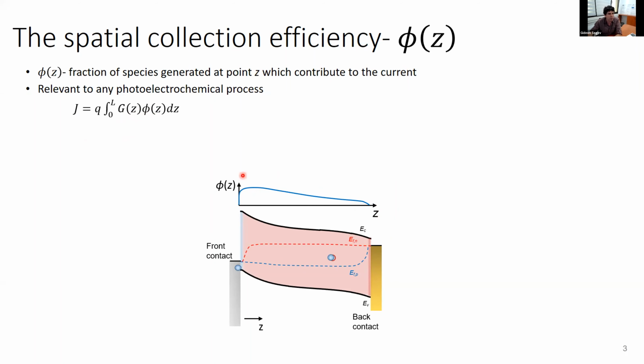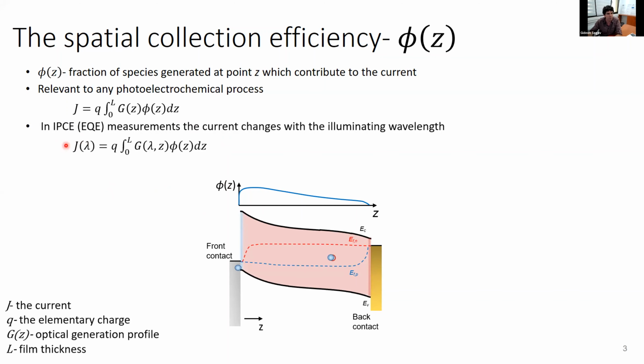The difficulty is that there are infinite number of solutions to this equation, so we need to get more information on the system. The way for us to do this is to measure quantum efficiency, or IPCE, depending on where you come from. You can give this a different term. Essentially, you measure the current as a function of the incident wavelength. Now, for every incident wavelength, you have a different integral that gives you more information on the system, so you can more easily perhaps converge onto the physical solution for the spatial collection efficiency.